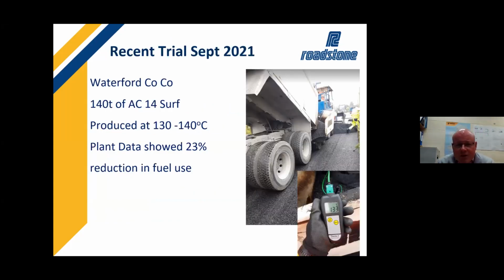So in September this year, we carried out a trial in Waterford. We made approximately 140 tons of AC14 surface course, and produced it at a temperature range of approximately 130 to 140 degrees centigrade.